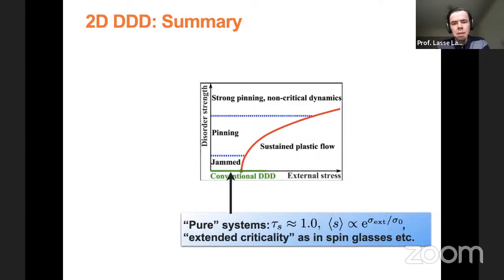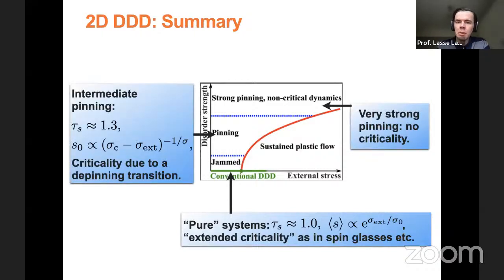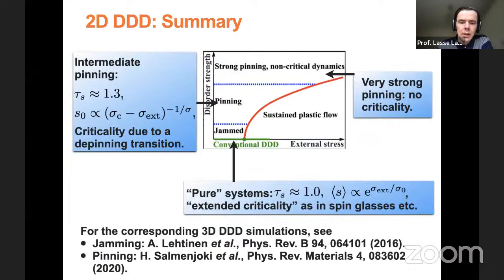Okay, so there's this summary of the phenomenology of this model that we are going to use for machine learning now. We're actually focusing on this pure system case where you have only the dislocations, no other defects, and see what you get as a result. Then of course we have also done some 3D simulations. Of course, in reality, these crystals would be three-dimensional, and in that case, the dislocations would be actually lines rather than points as in this simple 2D model. We can reproduce the same kind of phenomenology also in this 3D system, but it's much more complicated, much more computationally expensive to simulate. So it's a little bit more tricky in that sense.